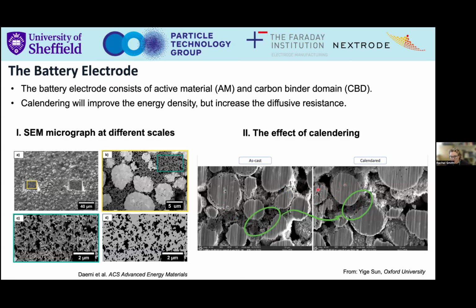Now, you can see here that, of course, we are affecting the active particles a little bit. You certainly want to minimize the breakage of these particles, but it is very challenging to not have any breakage. The pressures that you're using and the stress through the plane of the electrode make it difficult to achieve the calendaring that you want without breaking any particles. But that said, we want to try and minimize that effect. The main reason we're doing it is to squish up this CBD phase and bring the active particles closer together.